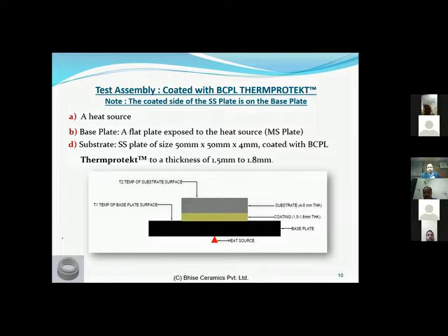Okay, amazing. Cool. So this is where we are installing the coating. This is a coated sample where it's on the heat, so it's on the base plate. We are heating the base plate, and as everyone knows, this is your typical heating system. This is your hot face of the lining or the heat source. This is your insulation lining, and this is your furnace exterior shell body, and this is the cold face temperature at the exterior of the furnace. So this is roughly what we are trying to mimic over here.